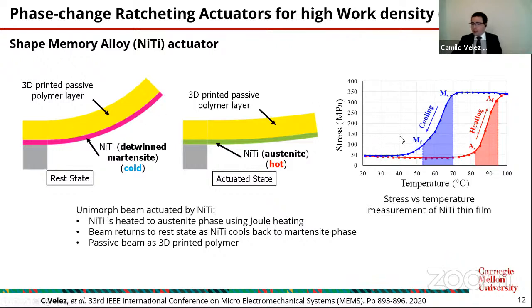The way to heat this up is by Joule heating. It means that we apply a current through the shape memory alloy, and by applying the current, we heat up the material. If we have a passive layer on top, the material is going to deform. If originally, because of the stress of the material, it is curling up, when you apply the current and heat up the material, it curls down. The reason it curls down is the stress mismatch between the shape memory alloy and the passive layer on top.